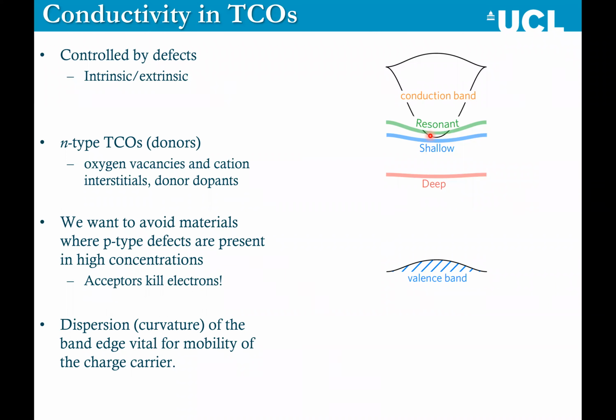So for N-type transparent conducting oxides, we need donors, so things that donate electrons to the system. So these are, in terms of intrinsic defects, these can be oxygen vacancies or cation interstitials, or we look at donor dopants, so a dopant that has one extra electron than what it is replacing. We also want to avoid materials where p-type defects are present in high concentrations, because of course acceptors will kill your excess electrons, killing your N-type conductivity.